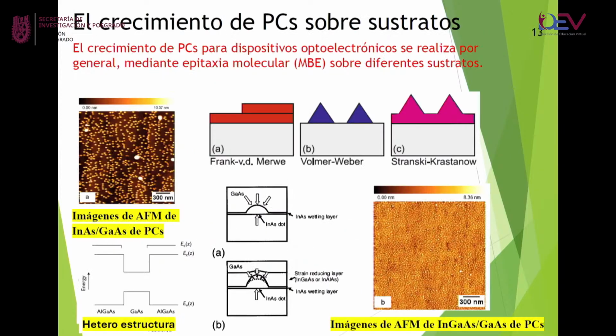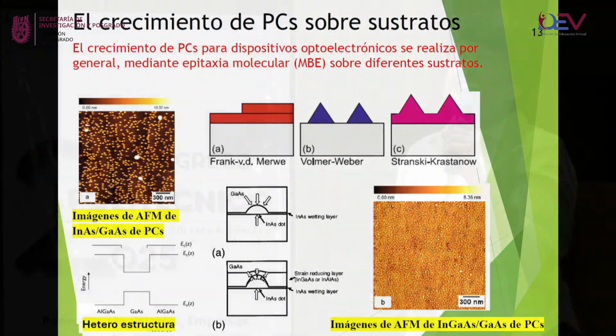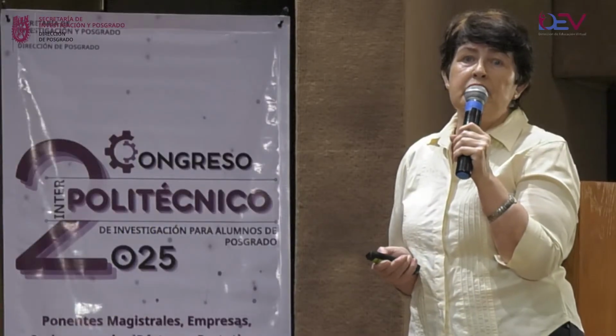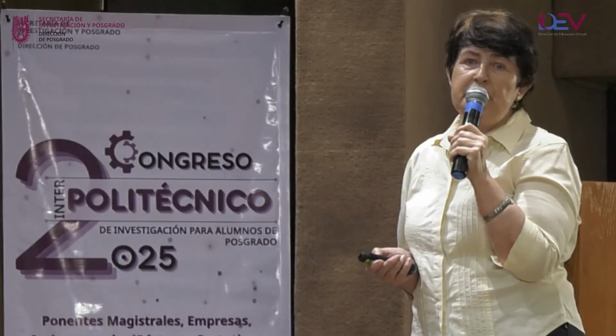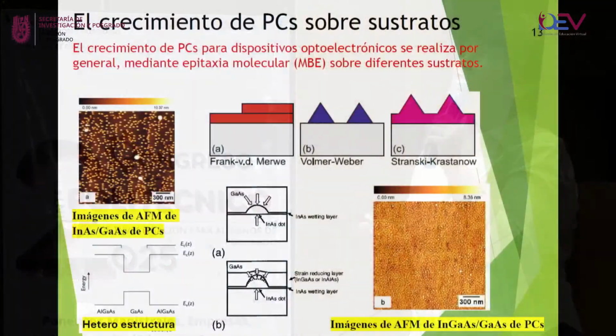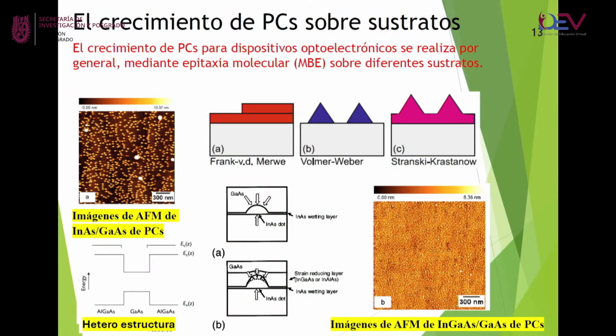Quantum dots in the case of semiconductor devices are produced by molecular beam epitaxy. It grows in a chamber in high vacuum. On some substrate, we grow quantum dots by the Stranski-Krastanov method. And you could see here uncovered quantum dots on the surface of the substrate.